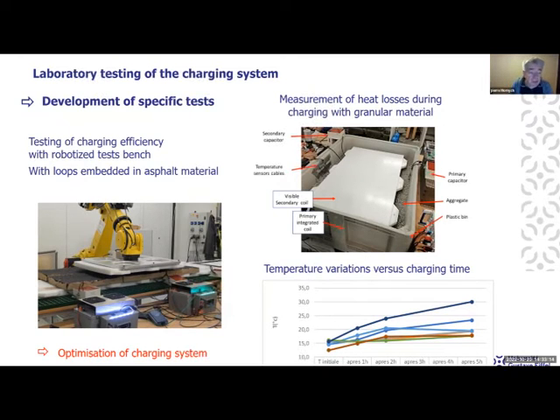So first we worked with Vedecom on the charging system itself. We did tests for testing the charging efficiency with the coils embedded in asphalt materials, using this robotized system that you see on the left. The bottom coils are embedded in the asphalt layer and the top coil is on this white plate and is moved by the robot arm to simulate the displacement of the car. We tested the performance in different conditions, with different thicknesses of asphalt material and different positions of the secondary coil, and in particular testing the effect of different misalignments between the primary and secondary coils. With this, it was possible to optimize the charging system.